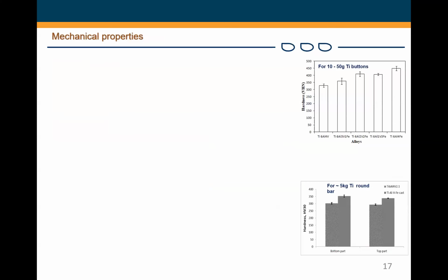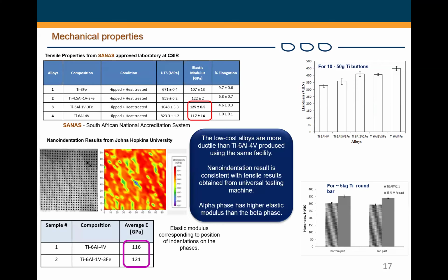So what does this mean in terms of mechanical properties? Remember, we started from 10 grams, we moved to 50 grams, and of course to about 5 kg. Just comparing the commercial grade with the experimental alloys, you can see the iron was even strengthening the alloys more. So you get more strength as you replace vanadium with iron, due to what we call solid solution strengthening. And at least we're happy that what is causing the strengthening is not the oxygen and nitrogen, because that would have been a disaster. And we carried out this experiment on the 5 kg alloy.